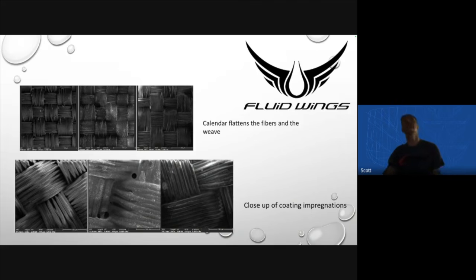And what you'll see, you can probably even see it here, is if you look up here and in there, you can see less gaps between these fibers. The more flat they are, the more they fill out. Below here is the coating impregnations. And you'll see here that the better the coating impregnation and the tighter the weave, the less gaps you get. But for example, here on this one, you've actually got a gap in the coating. So that's where permeability comes from, or porosity. Is small imperfections in the coating, small imperfections in the weave. Ideally, we're making this fabric as low permeability as we can get it.